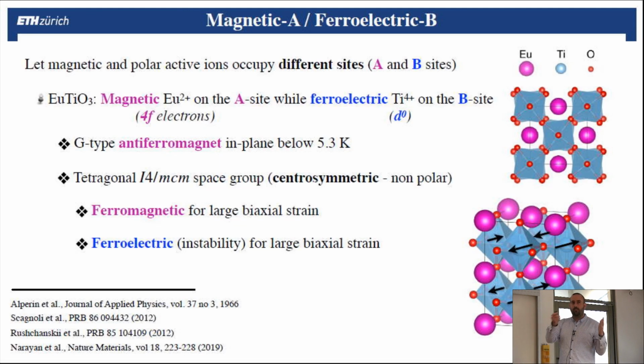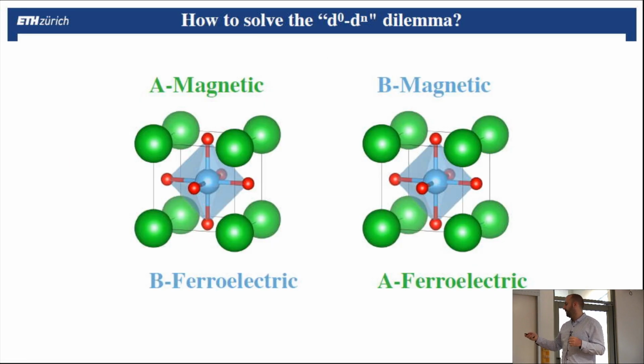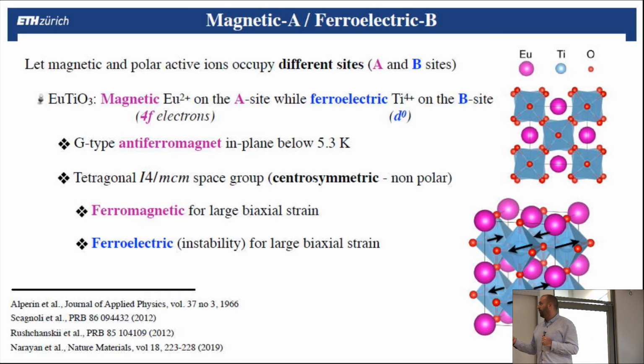And I will show you two examples of material that correspond to each of these cases. So the first one is called europium titanate, which is magnetic and ferroelectric, but under certain conditions. Actually, it is antiferromagnetic with the magnetic ordering in plane, as you can see here. So this is the crystal structure, and here you have the A site, that is the magnetic one. I'm sorry, it just shifted by half of the unit cell, that's why you don't see this big atom in the corner, so don't be confused by that.